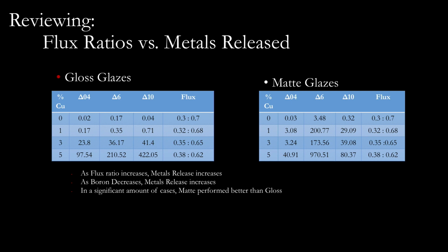This chart is very simplified but contains some very powerful information. So you've seen this before earlier. It's the metals release at the various percentages, but what we've included on the far right column is the flux ratio when you begin to account for copper as an R2O. When you do that, the flux ratio begins to increase. The higher that flux ratio, the more metal begins to get released.